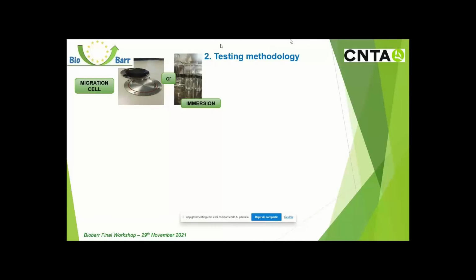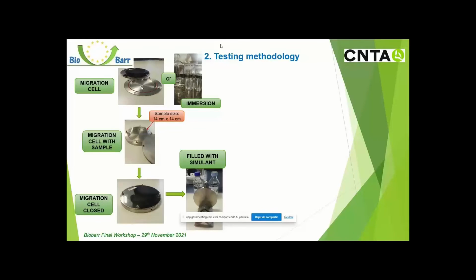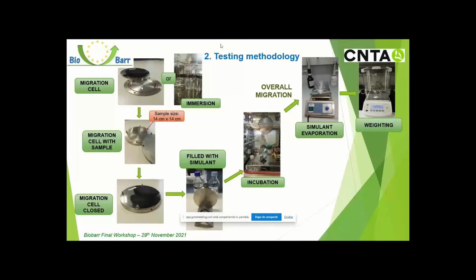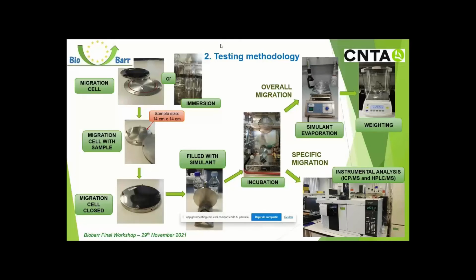So we are going through the testing methodology. Two types of testing have been performed within the project. We have the testing by total immersion, in which both sides of the sample are in contact with the simulant, or the single-side testing using a migration cell. In this case, only one surface of the material is in contact with the simulant. Afterwards, a 14 centimeters by 14 centimeters film sample is placed in the migration cell. Then it's closed and filled with a simulant. Afterwards, the migration cells are incubated in an oven, and for the overall migration, there is a stage of evaporation of the simulant and weighing, and for the specific migration, there is an instrumental analysis.